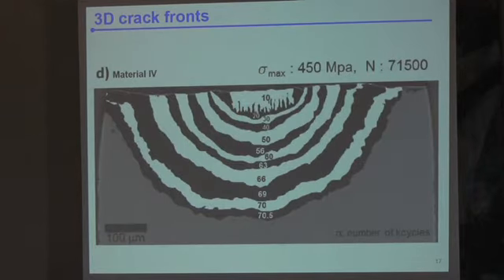The only difference we got was from this one, which is material 4, and I'm not sure you can spot it at once. There is a difference in the angle that the crack front makes with the surface, which is now no longer 90 degrees. And the difference it makes is that the crack aspect ratio will be different in this case.